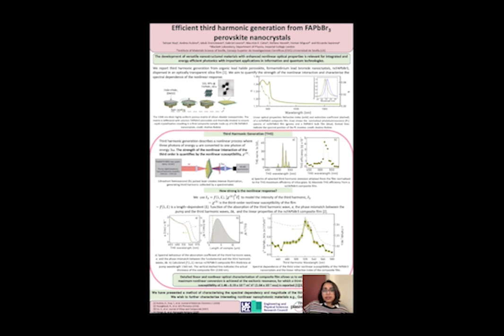over the sample thickness. Finally, by considering the volume distribution of the nanocrystals in the silica matrix, the maximum third-order nonlinear susceptibility of the formamidinium lead bromide nanocrystal was found to be 1.46 times 10 to the power of minus 19 meter squared over volt squared. This is the same order of magnitude as the inorganic lead halide perovskite nanocrystals.